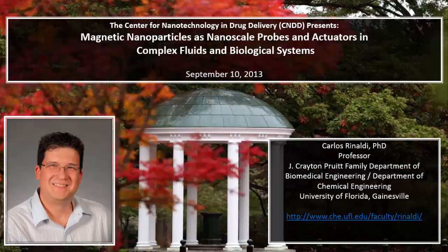using external heating. So this seems to indicate that immediately upon turning on the field, something has happened in the vicinity of the nanoparticle, which has forced the polynipam to go from hydrophilic to hydrophobic. So it has crossed its lower critical solution temperature, let's say.